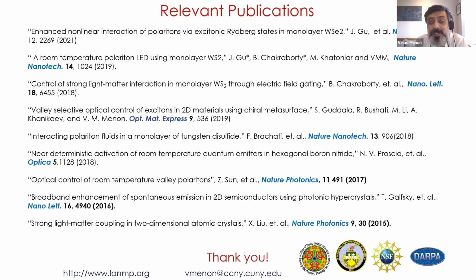Important thing that we've learned is that we need to encapsulate the 2D semiconductors like tungsten disulfide and so on between boron nitride layers, and that essentially ensures that these materials have good optical responses. Substrate cleaning does matter. You can find the substrate cleaning recipes in some of our papers on how it is done, and the key here is that you need to have substrates that are, of course, clean, but again, like I said, you can do it in an ambient environment.